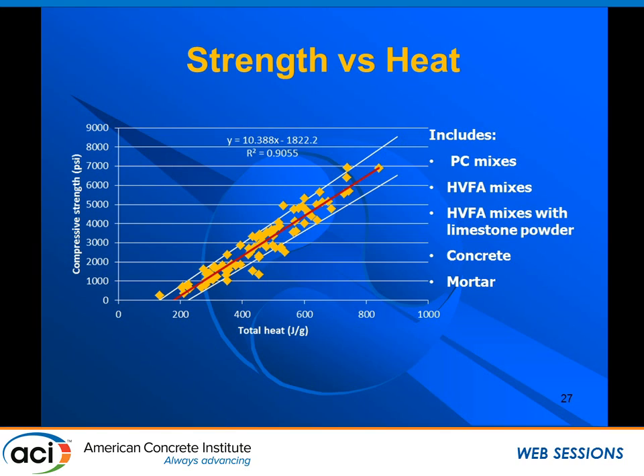What we did is total heat, let's say, at 1 day, and compressive strength at 1 day. When we measured compressive strength of concrete, the total heat was measured on the sieved mortar. When we measured the compressive strength of the mortar, the total heat was measured on the mortar or on the paste. It's a very good correlation. Here is the 95% confidence interval. But for the paste that we just had with the nanoparticles, I didn't have 7-day calorimetry data.